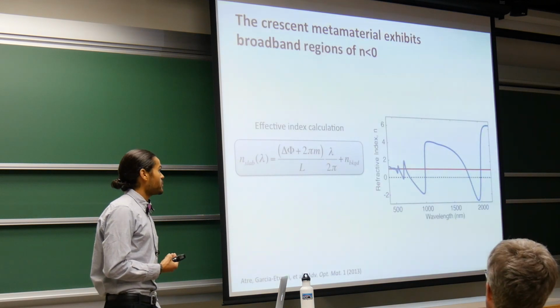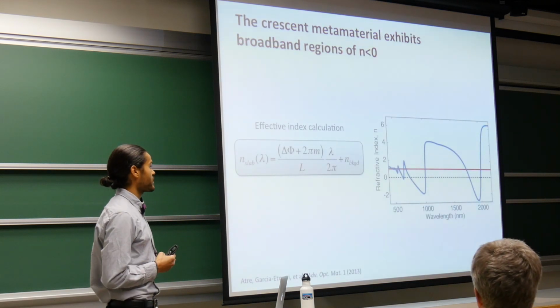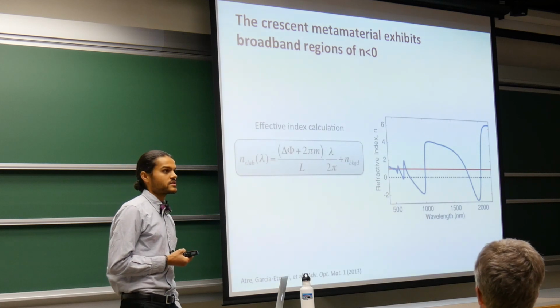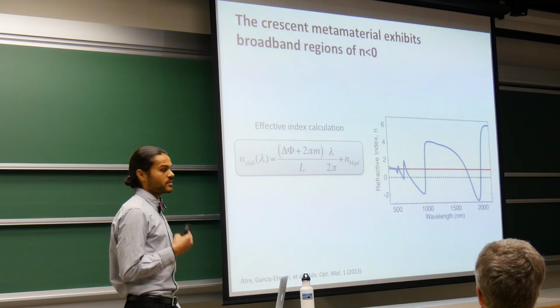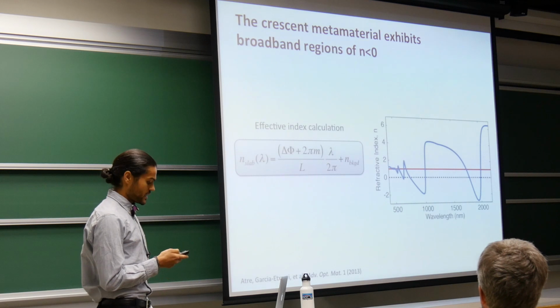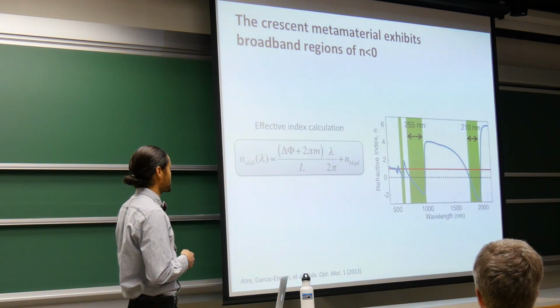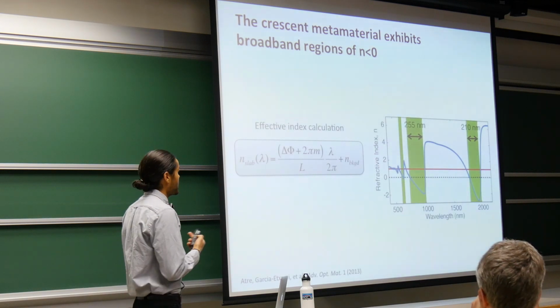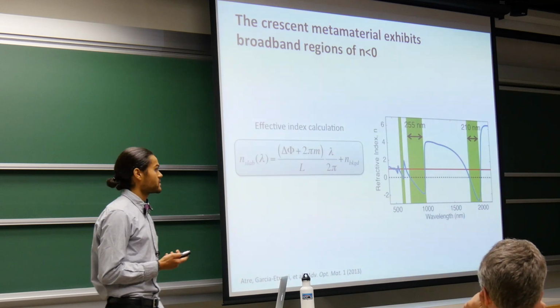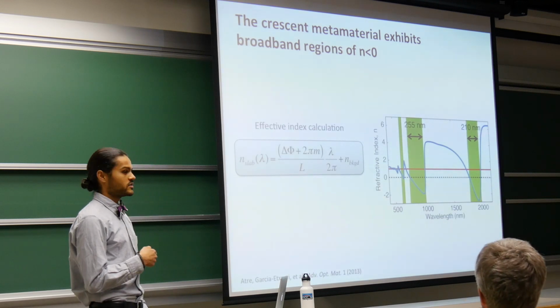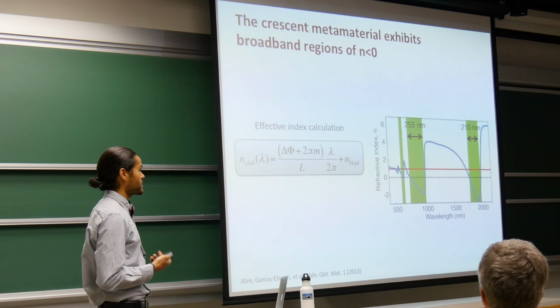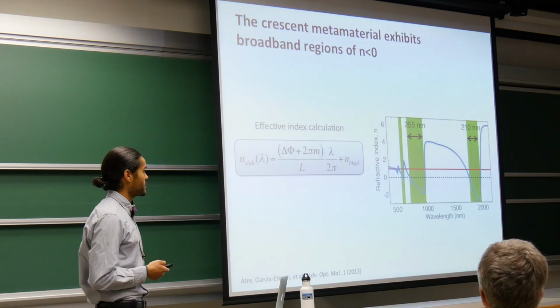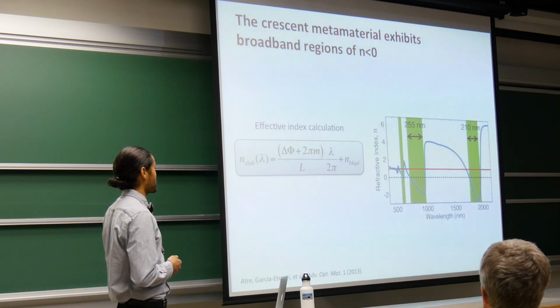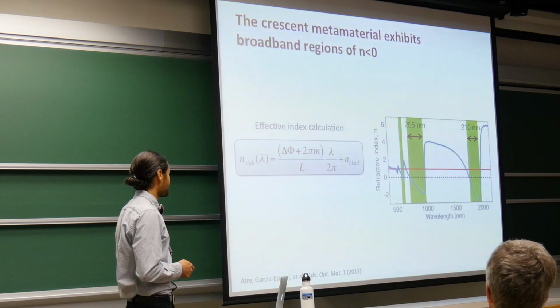And when we do that, we find that throughout visible and near-infrared frequencies, there are multiple regions where the index drops below 1 and below 0. In fact, within this region below 1,000 nanometers, we see that we have a negative index regime with a 255 nanometer bandwidth, which more than doubles the previous largest bandwidth achieved in this frequency range.